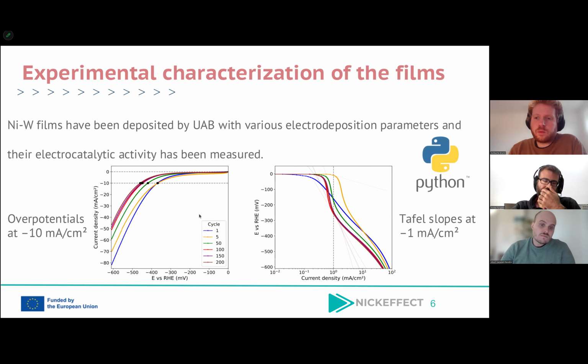Then the first step was to write a small Python script to automate the extraction of some quantities from these curves. The first quantity that we extracted was the overpotential at minus 10 milliamp per centimeter square. And then we also got the Tafel slopes at minus 1 milliamp per centimeter square. We got that for 6 LSV cycles.